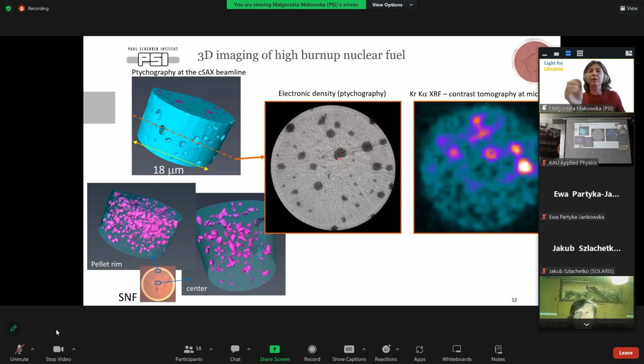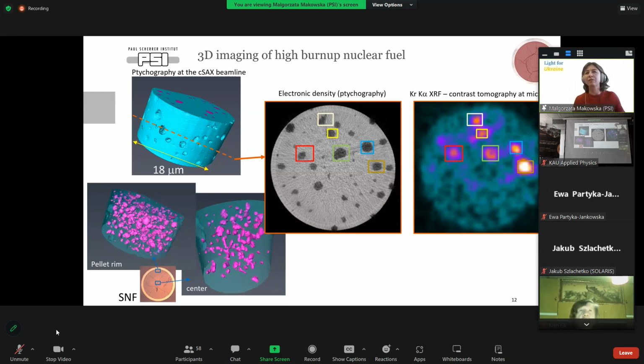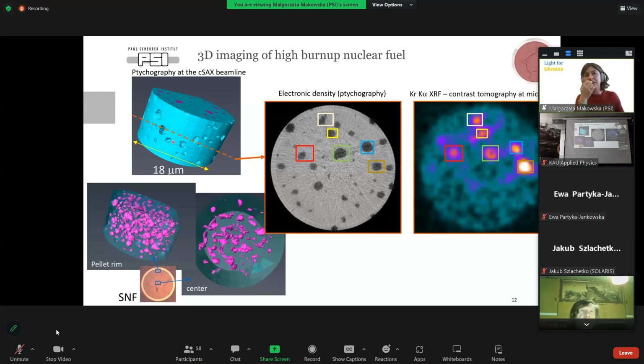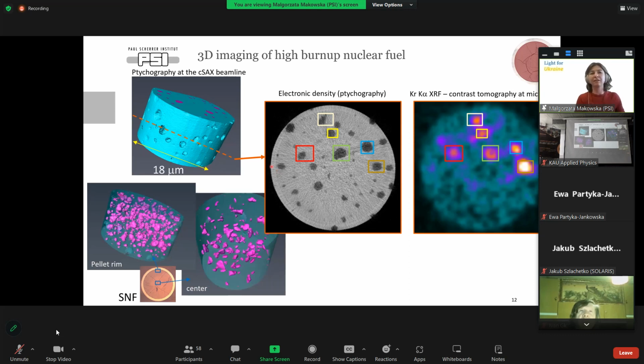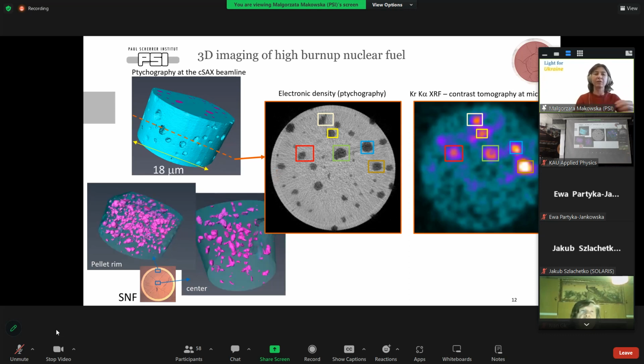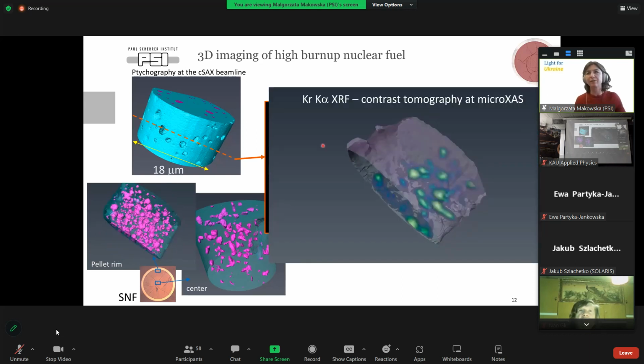And what we did, we took the same sample to microXAS and we performed this tomographic microscopy based on fluorescence contrast, but also on diffraction contrast. And then we could match exactly the same slices from ptychography, which gives us very high resolution, with much poorer resolution but fluorescence contrast. And we could really recognize that these features that we observed here were filled with krypton. So there are pores filled with fission gases. And then depending on the burnup of the fuel, depending on the position, we can analyze their pressure, concentration, and more things. Yeah, and in fact, we did it really in 3D.